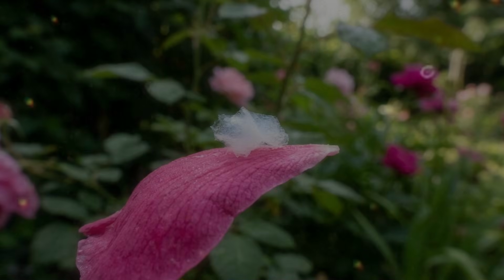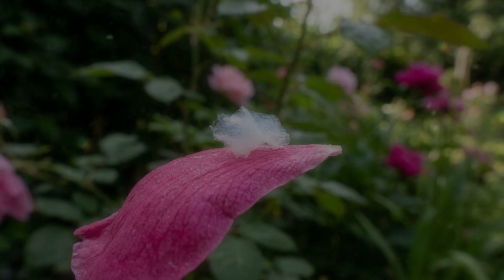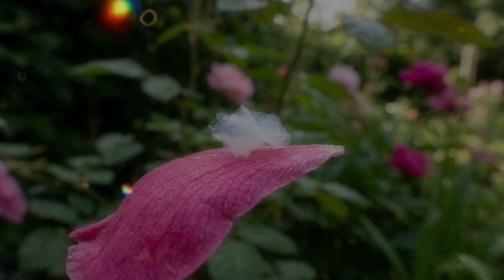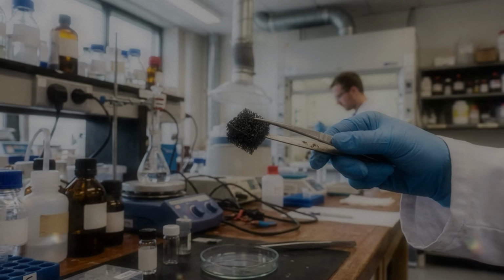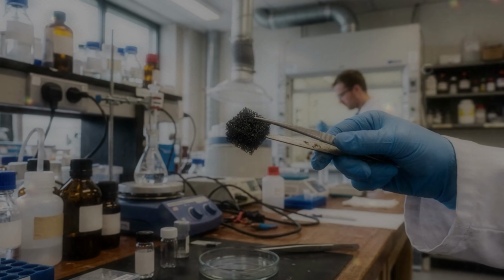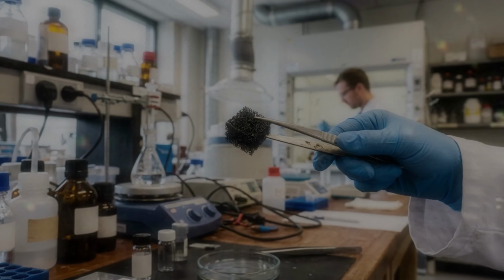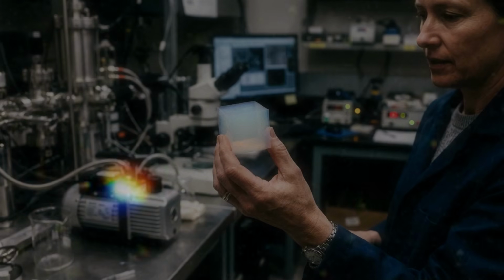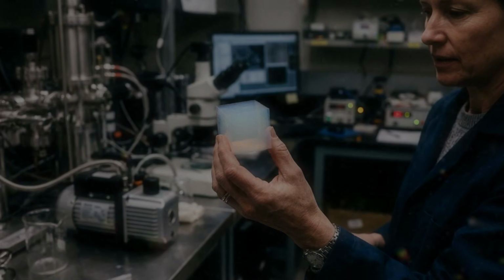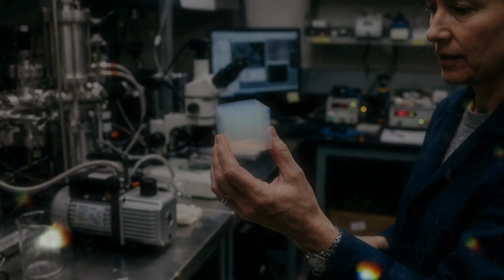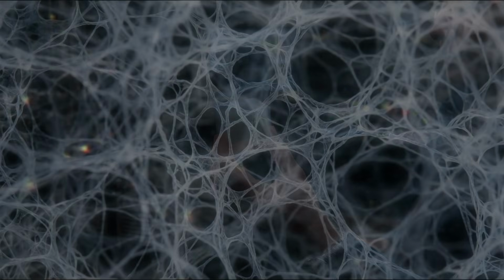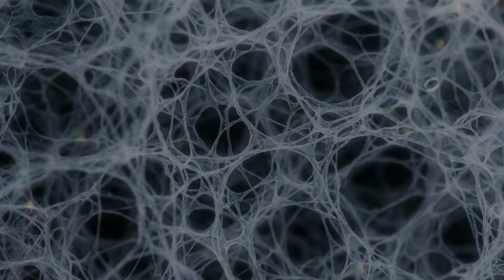The black appearance can also help the material absorb light and convert some of that energy into heat. This can be useful in systems designed for heating, evaporation, sensing, or energy conversion. At the same time, the porous structure may remain a poor conductor of heat across the entire sample because the solid paths are sparse and interrupted by countless interfaces.